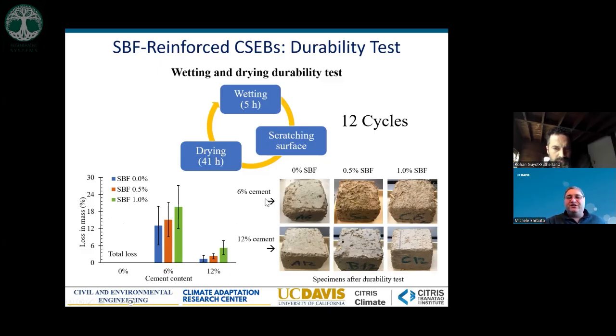So there is some attention that needs to be paid to the addition of fibers in this material, and that has to be balanced because fundamentally, I wouldn't generally recommend the usage of 12% cement in these materials, except the base material that we were using in southern Louisiana was already a low quality soil and with the high requirement in strength.